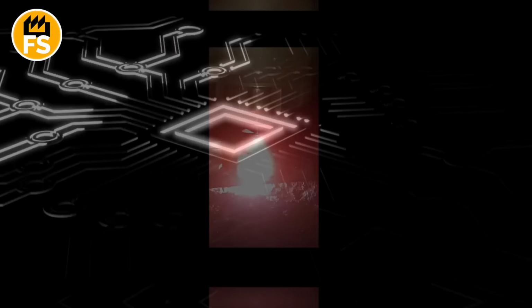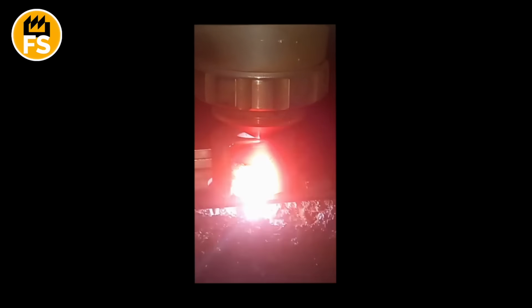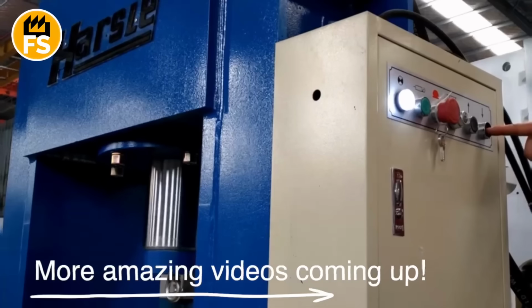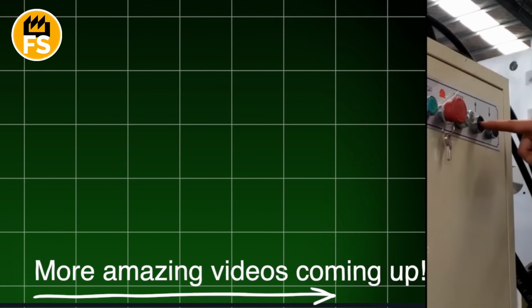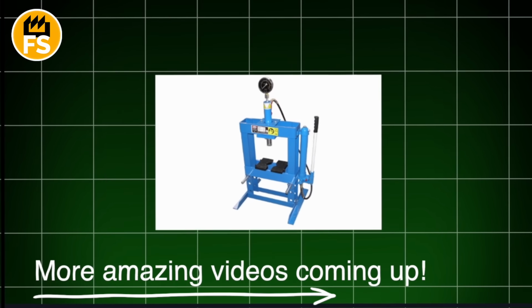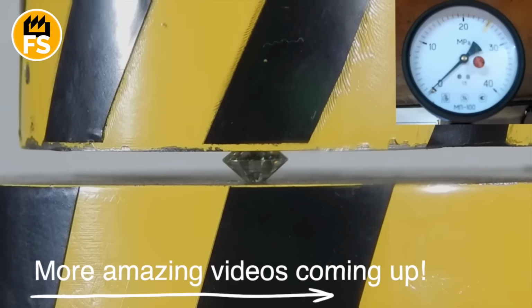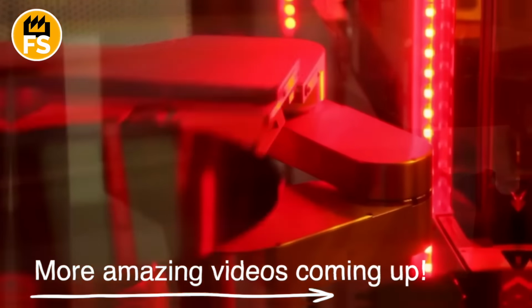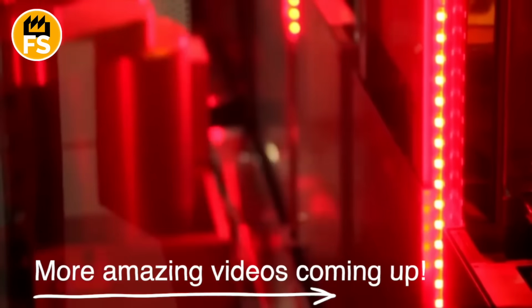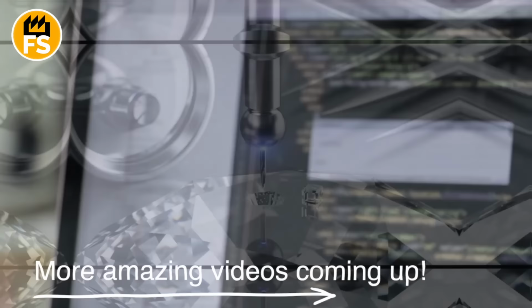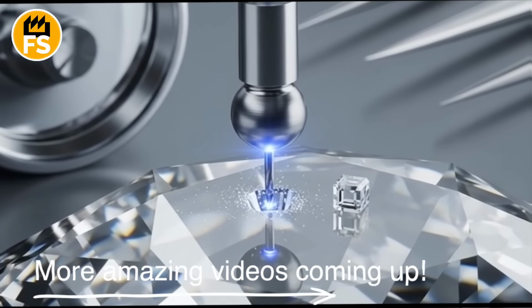The wavelength of 1030 nanometers in the infrared spectrum penetrates exactly 1/10 of a micron deep and removes an ultra-thin layer with 1 micron precision. The result? Perfectly smooth edges without burrs. In industry, this is done on machines from Coherent or Trumpf. They cut jewelry-grade diamonds for a $50,000 ring, or lab-grown diamonds for semiconductor chips. The process runs cold. The surface heats to a maximum of 100 degrees Fahrenheit, so there's no deformation or material stress. The speed's modest. For diamond, we're talking 1 cubic millimeter per minute, but the precision is surgical.